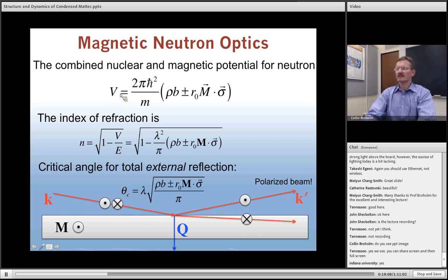And this is now the interaction potential of the form that we've been discussing when we talked about neutron optics. Remember, we introduced the Fermi pseudopotential, which was this very spiky function that had a delta function at the location of each nucleus. And then we said that if we were in a situation where interference effects were not important, and then we discussed how one could get into that limit, then we could think about the neutron-nuclear interaction as a smeared potential, which would not know about, if you will, the features that were occurring at the atomic scale.